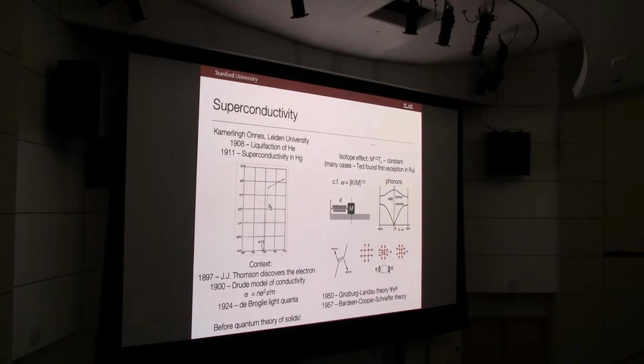So this kind of picture can lead to the finding that if I take two electrons, I can bind them with equal and opposite spin and momentum into so-called Cooper pairs and gain energy, or condensation energy, with this. And if I can come up with a way to make a macroscopic quantum coherent state using these Cooper pairs, what followed was the development eventually of a microscopic theory of superconductivity using this electron-phonon mechanism. Preceded by almost a decade first by an effective phenomenological theory taking this notion that you have this macroscopic quantum wave function.